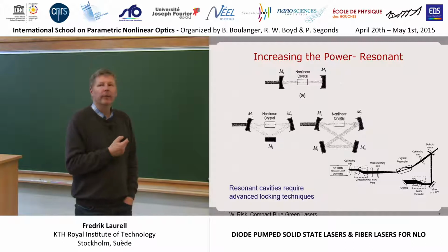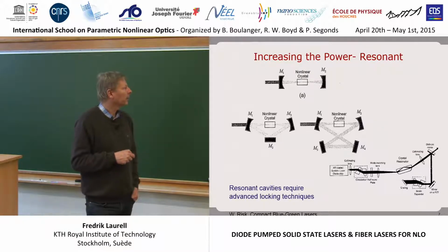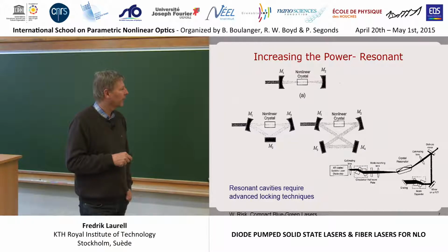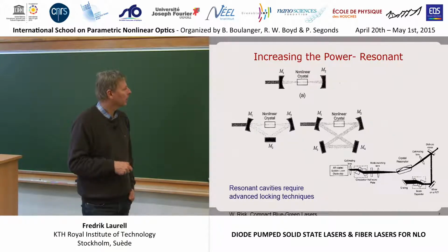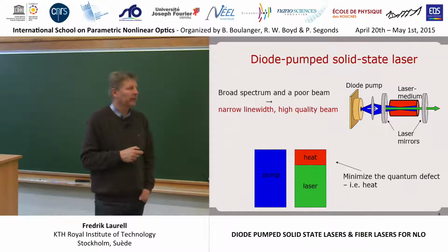And then now when we work with the diode lasers, they have low output power, and some of the crystals have low nonlinearities, particularly it seems like those that are very robust to power have low nonlinearities. Then you have to build various kinds of cavities to enhance the power. But of course, resonant cavities already put a lot of additional requirements on your laser. So you need locking techniques, and they can be successful or less successful. Okay, so that was the simplest laser.